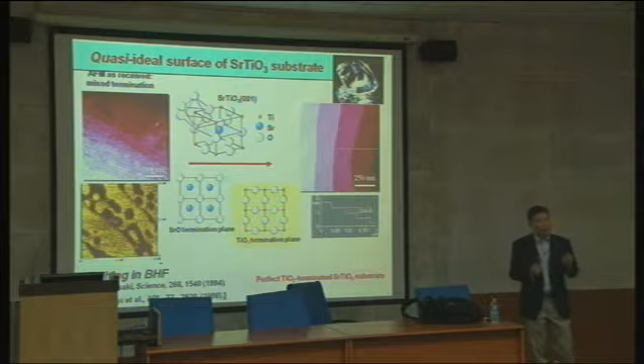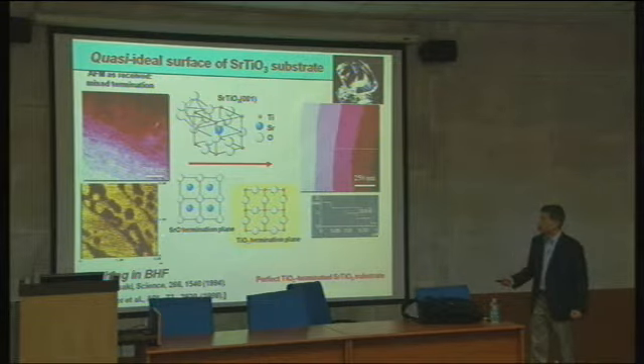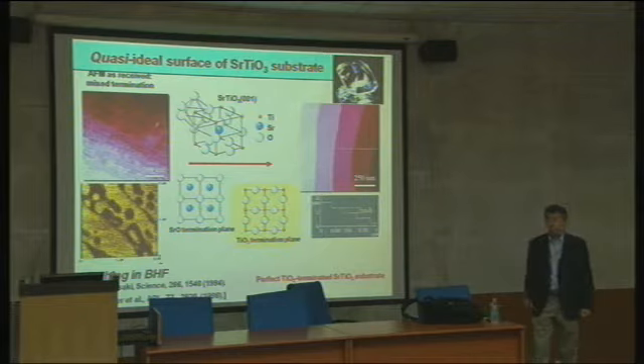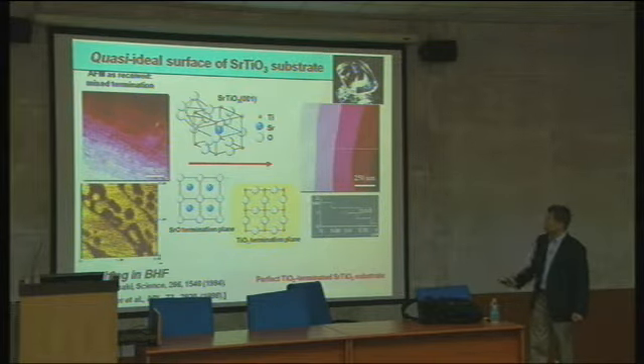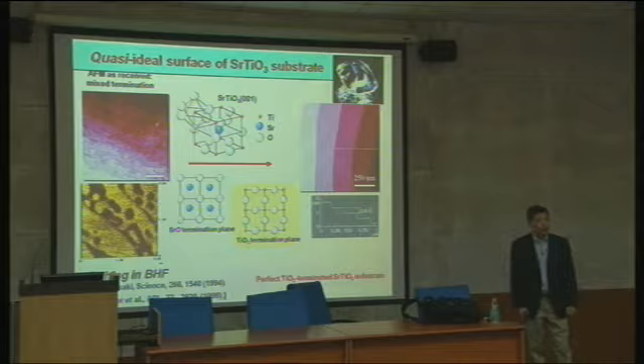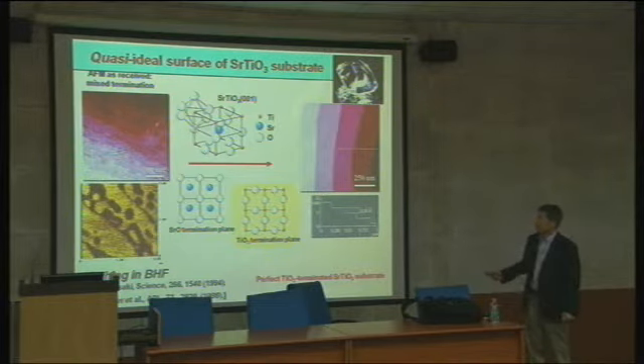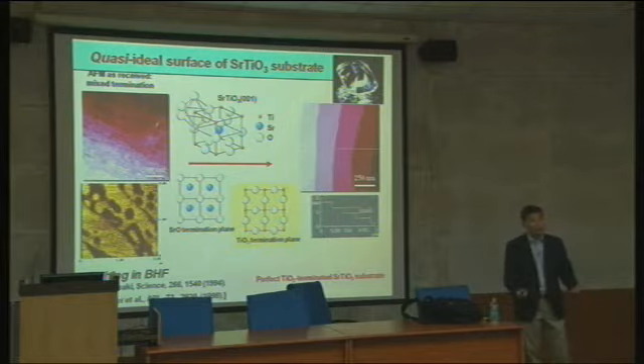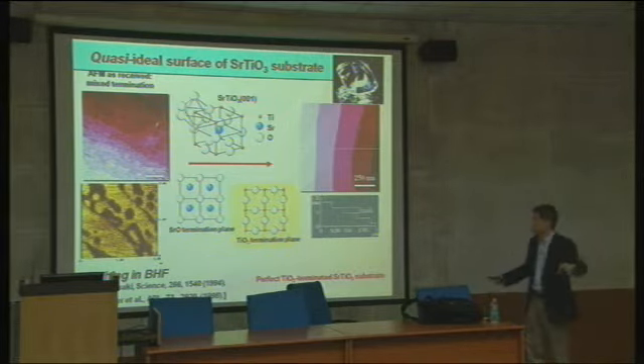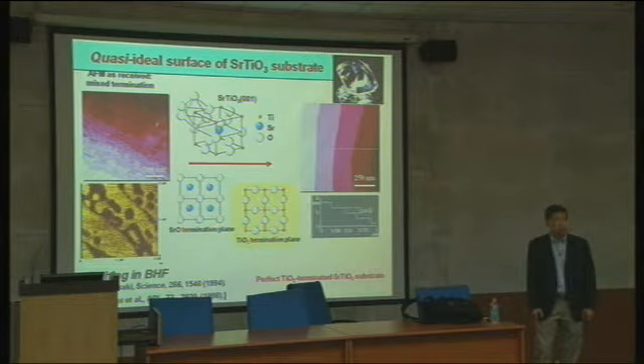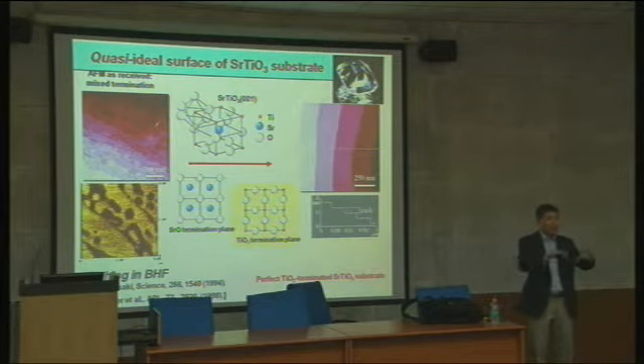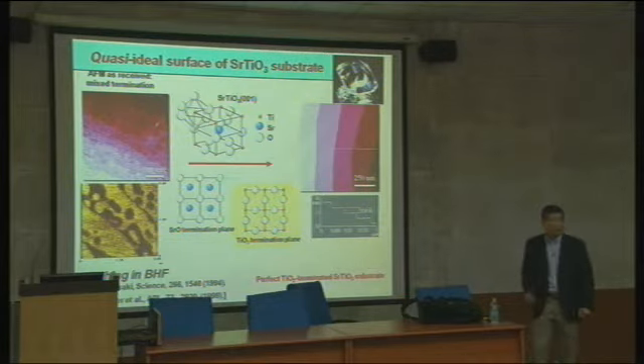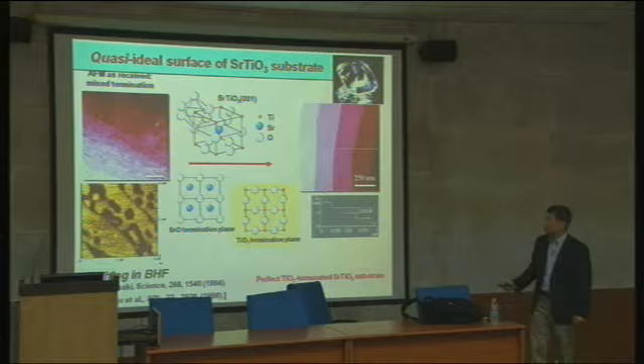Okay? There's a strontium oxide termination, strontium 1, oxygen 1. You look at this surface, the titanium O2 termination, it's 2 oxygen, 1 titanium, TiO2 termination. When you polish those things, the surface looks like this, a mixed termination. In a certain region, the TiO2 looks like this, in another region it looks like this. When you heat it up at high temperature, your atoms move around, forming large patches of different regions. This region is a titanium termination, TiO2, and this region, strontium termination.